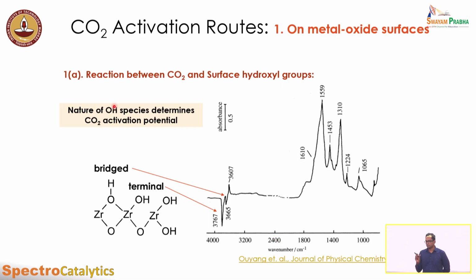This OH has particular vibrations, and the IR has a frequency range of 400 to 4000 inverse centimeters wavenumber. When we get the right amount of energy, that energy is absorbed and the bond vibrates at a very high rate, and that's how we identify this kind of species. This is a different spectra - meaning we look at the spectrum of the pristine catalyst, the zirconium oxide, where there was no CO2, then we add CO2 and subtract it from the original.